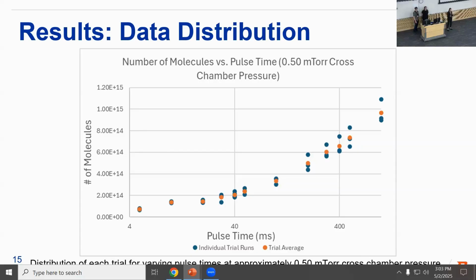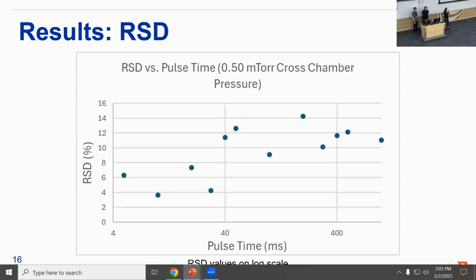As you can tell, the distribution varies significantly by pulse time. Shorter pulse times tend to have a more consistent result, while the longer pulse times showed greater variability. This variability in longer pulse times suggests that maintaining precision in gas dosage becomes a challenge when the pulse time duration increases. Here we have the relative standard deviation values plotted on a logarithmic scale.